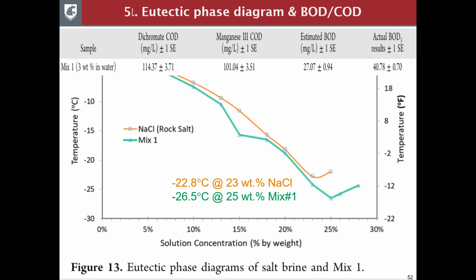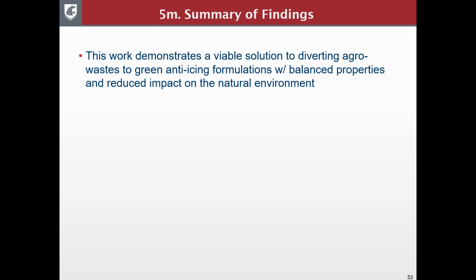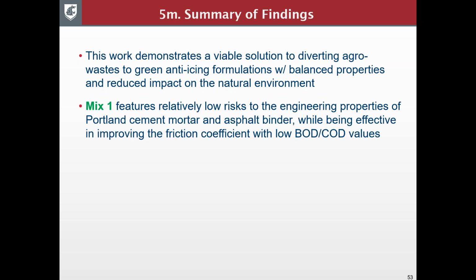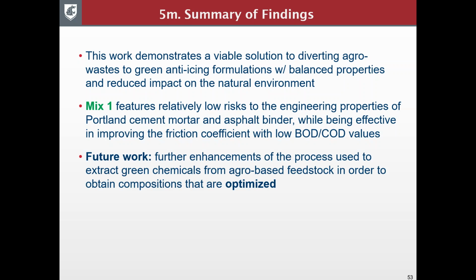So to summarize, this case study demonstrates a viable solution to diverting agro waste to green anti-icing formulations with balanced properties and reduced impacts on the natural environment. And mix 1 features relatively low risk to engineering properties of Portland cement mortar and asphalt binder, while being effective in improving friction coefficient and with relatively low BOD, COD values. So the future work should further enhance the process to extract the green chemicals, since we know which ones are the effective compounds now. Then depending on the specific user priorities, we can optimize or redefine the optimum formulation.